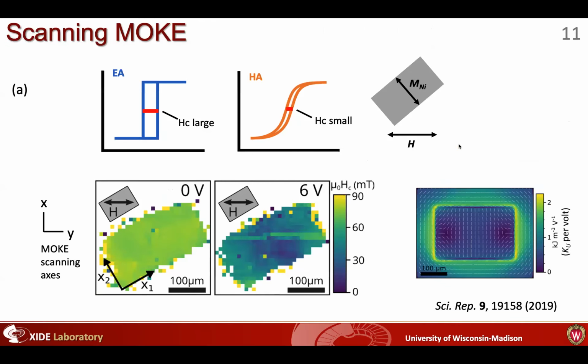We also did this scanning MOKE where you can see with the color bar, the strongest effect is right in the center of the electrode. So we rotate slightly off the long axis of the electrode and just show with voltage at 0 volts, we're pretty uniform in our anisotropy, but at 6 volts, we do indeed observe this stronger effect right in the middle.